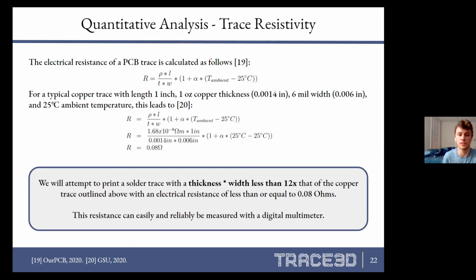From this calculation, we decided to set a goal for our own system that we will be able to print a solder trace with a thickness times width of less than 12 times that of the copper trace outlined above, that being due to the higher resistivity of the solder trace we'll be printing. And we can easily and reliably measure this with a multimeter in order to confirm that characteristic.